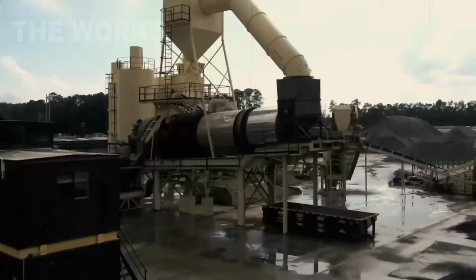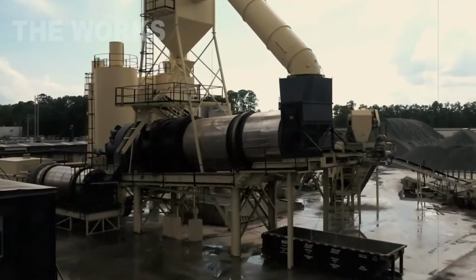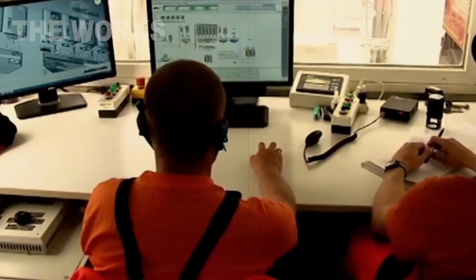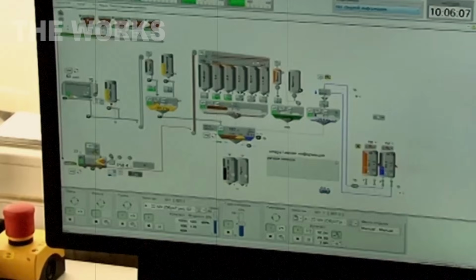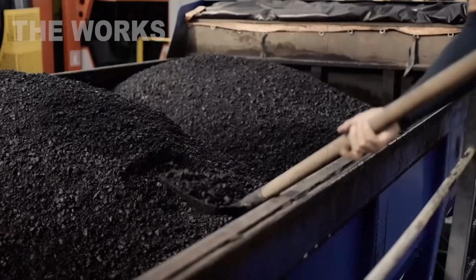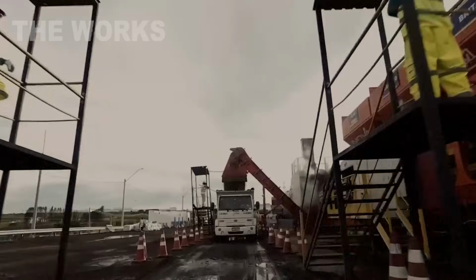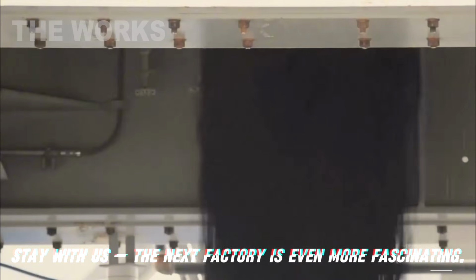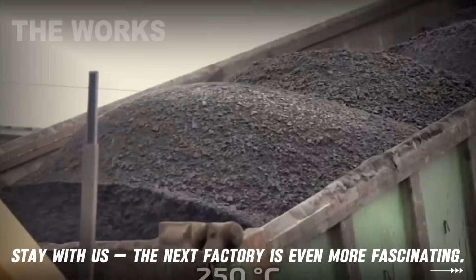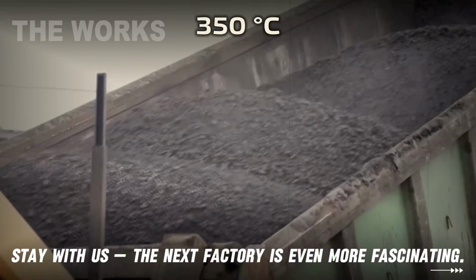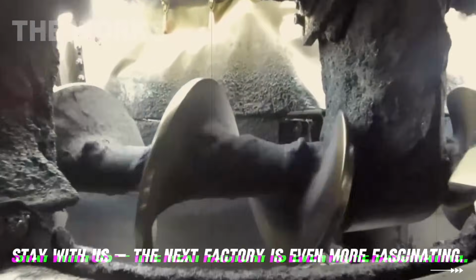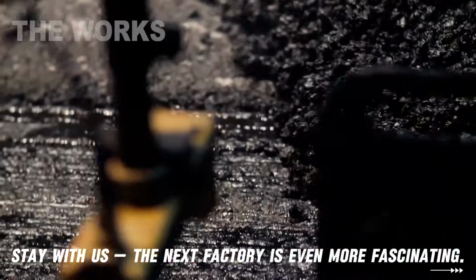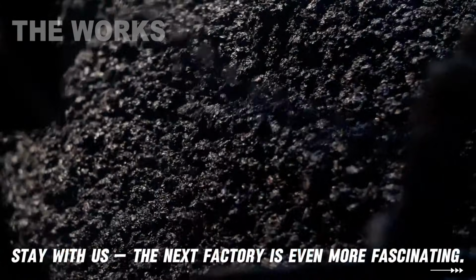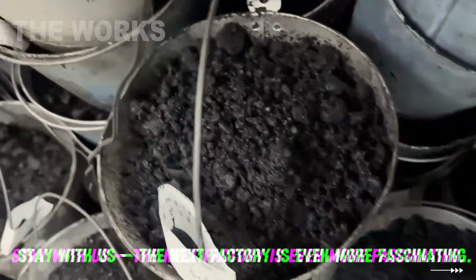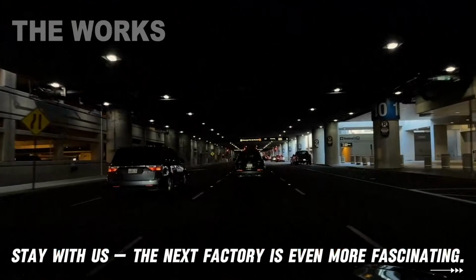That's why the technology has a concept called penetration, how deep a needle enters a sample at a given temperature and load. Engineers tweak the ratio of light and heavy fractions, add polymer modifiers to get a material that won't flow in the heat and won't turn brittle in the cold. In massive mixers, bitumen is heated to temperatures from 450 to 650 degrees Fahrenheit, and under intense mixing, they add modifiers, mineral powder, sometimes acidic or alkaline additives to stabilize the structure. That's how polymer-modified bitumens are born, for high-performance roads, airfields, bridge expansion joints.